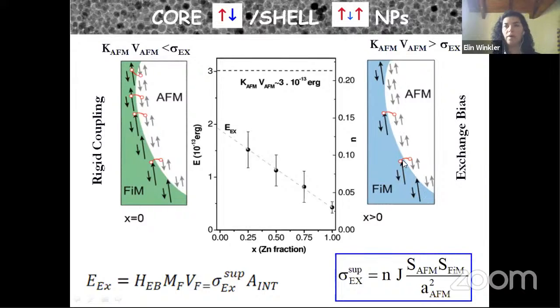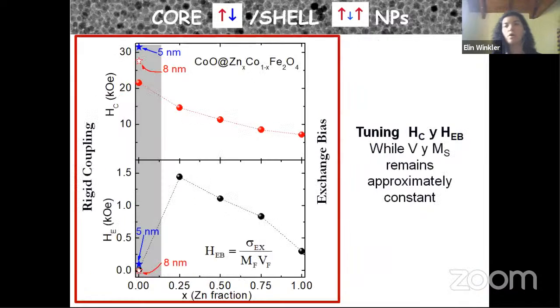Why? Because when you fabricate a system and make some calculation, you expect a very large exchange interaction, and usually the exchange bias field is about 10 times smaller than what you expected. And from this calculation, you obtain that result. That means that not all the spins at the interface are locked and induce this exchange interaction. So by systematically changing the shell stoichiometry of the core-shell nanoparticle, we can systematically tune the coercive field, and we can also modulate the exchange bias coupling.